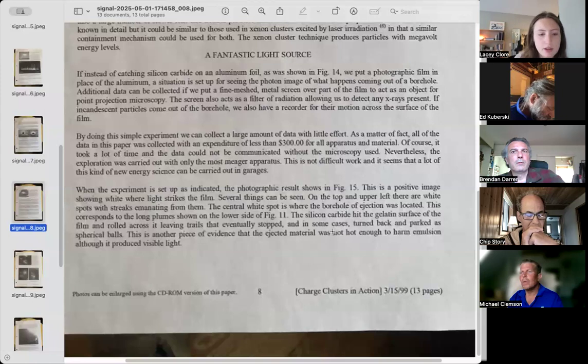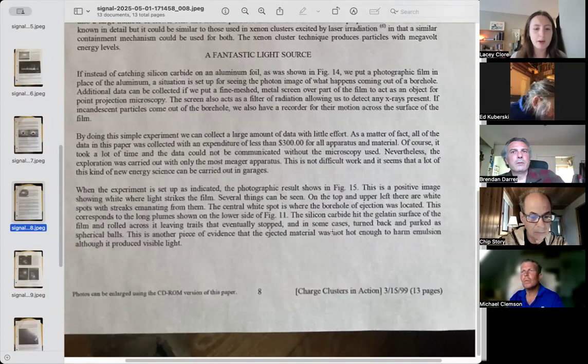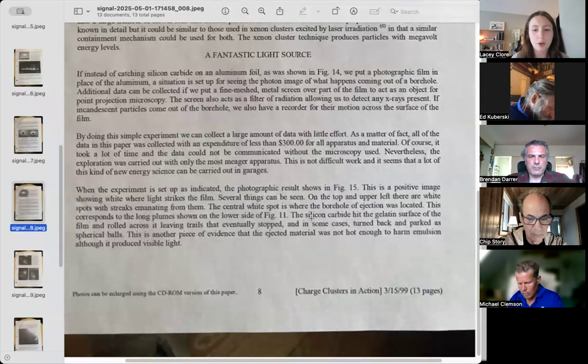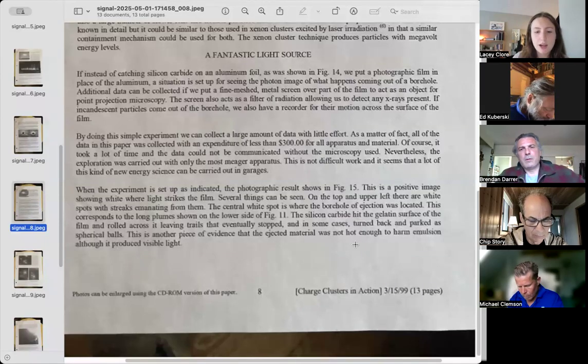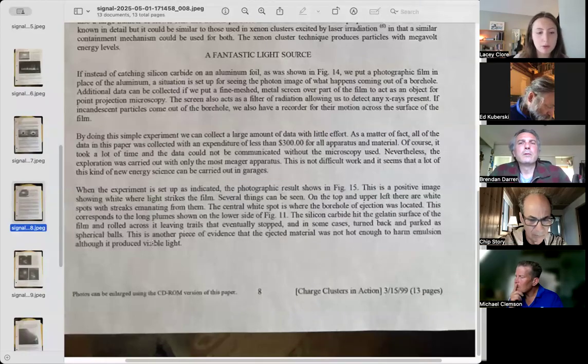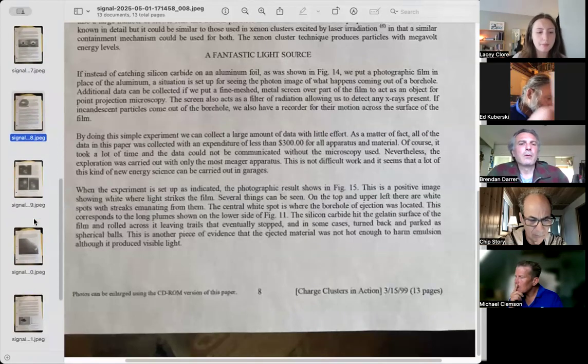This is a positive image showing white where light strikes the film. Several things can be seen. On the top and upper left, there are white spots with streaks emanating from them. The central white spot is where the borehole of ejection was located. This corresponds to the long plumes shown on the lower side of figure 11. The silicon carbide hit the gelatin surface of the film and rolled across it, leaving trails that eventually stopped, and in some cases turned back and parked as spherical balls. This is another piece of evidence that the ejected material was not hot enough to harm the emulsion, although it produced visible light.